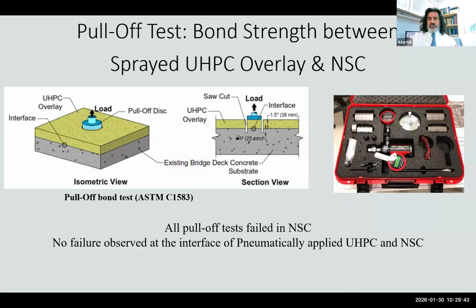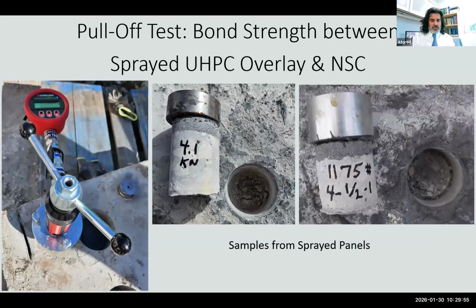We've done direct tension tests. We sprayed or cast UHPC on top of normal strength concrete, and then did a pull test. These are some examples of it. I can tell you, we never see the failure take place at the boundary. It's always in the normal strength concrete. There were a couple of cases where the failure took place at the boundary, but the reason was that there was still reinforcement, so the surface area was decreased. But this is something that others have reported too.